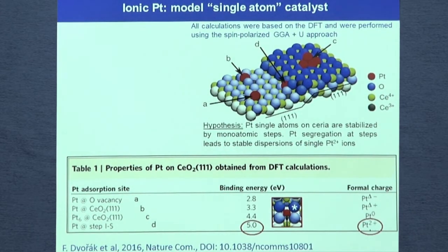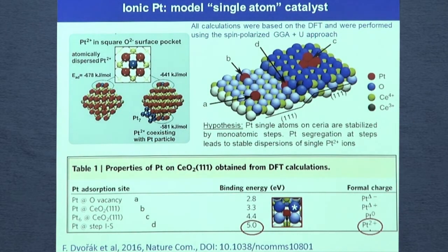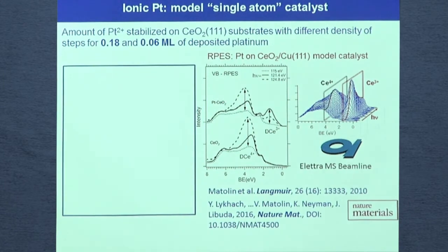Well, the model is here. We can check different types of platinum at the surface, the platinum at oxygen vacancies, by calculating binding energy of platinum, which is 2.8 eV. If the platinum is on the terrace, on the flat surface, the binding energy is here. Platinum in nanoparticles, binding energy, and the platinums at the stoichiometric steps, the binding energy is 5.0 eV, which means that again we have a square for oxygen, exactly as in the case of the small nanoparticles of platinum. So this model, flat, and the particles are going well together.